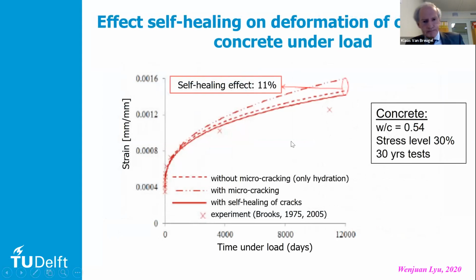Well, this has been put in a model, in the lattice model, and she did the calculations on the creep strain of tests over a period of 30 years, simulating tests of Brooks, who did the tests in 1975 already. And what she found is that if you look at these strain curves, there is one curve with no microcracking. Then there is a curve with the microcracking. Then you have extra creep.